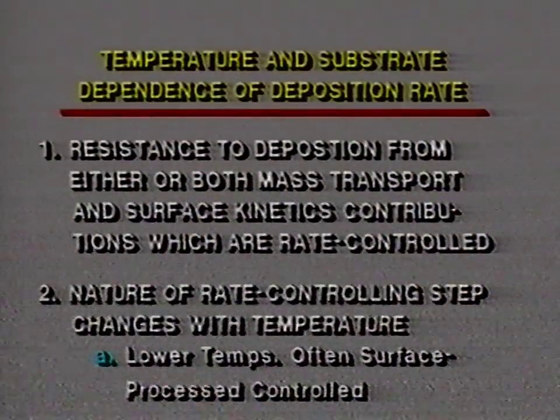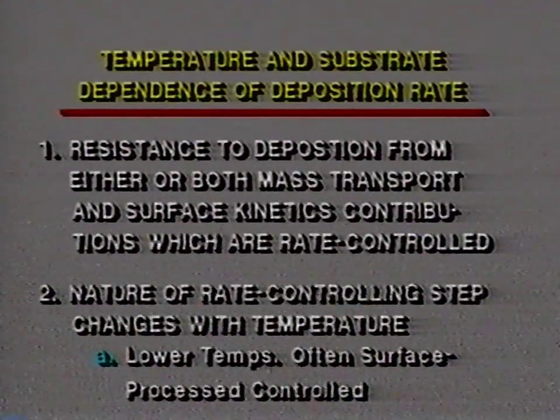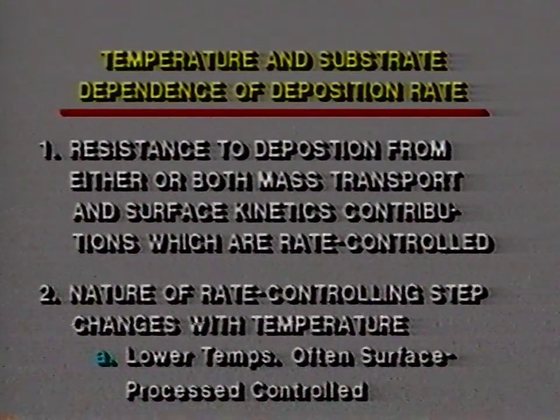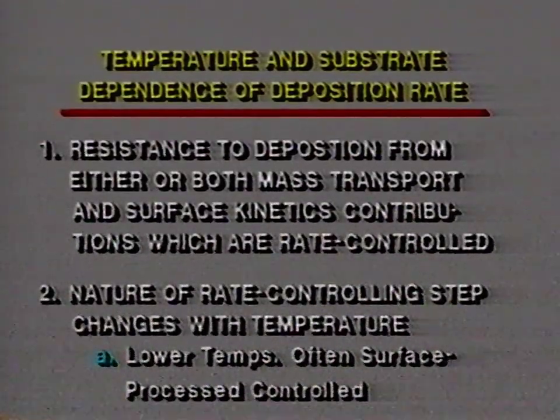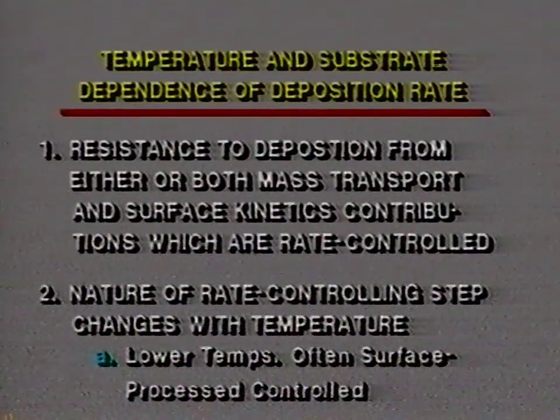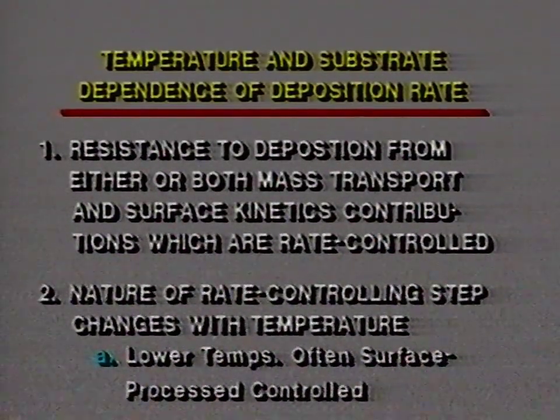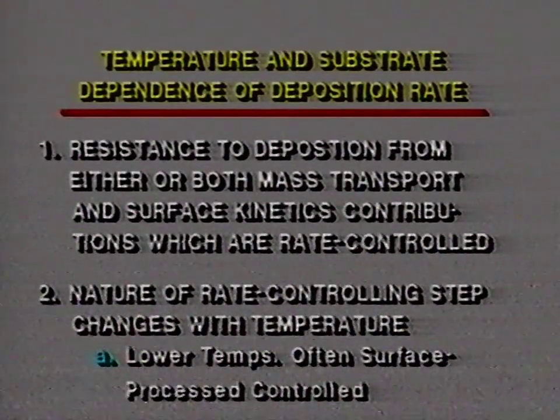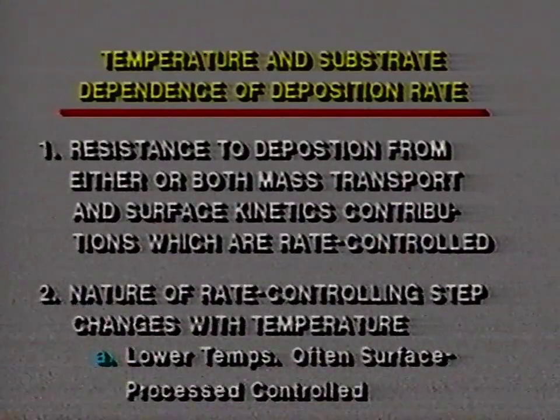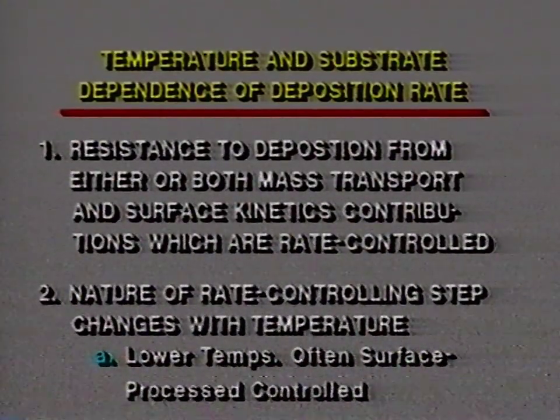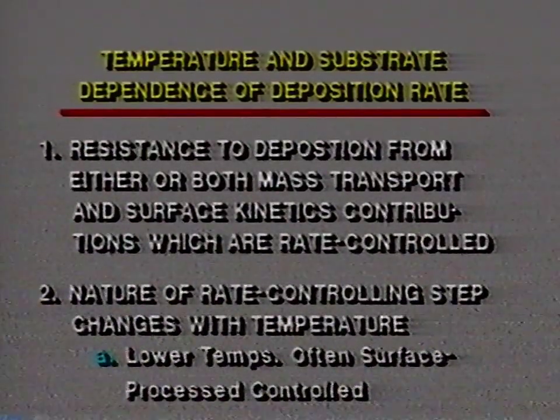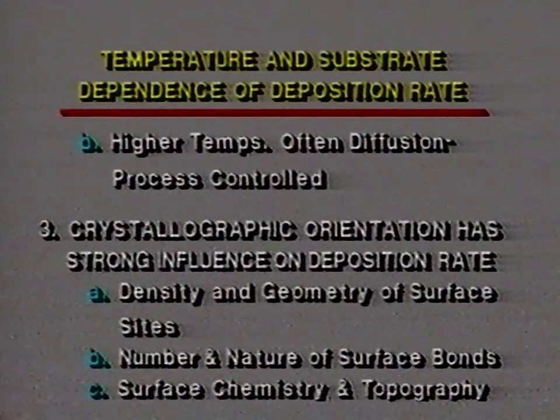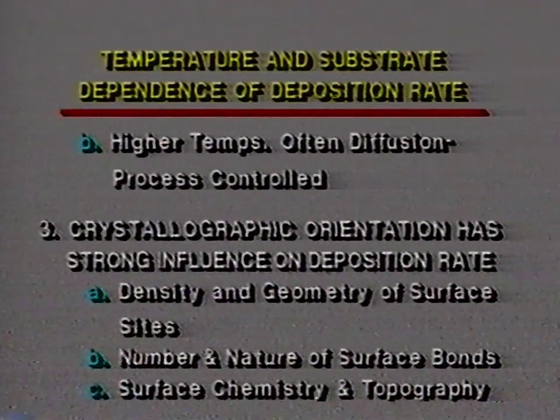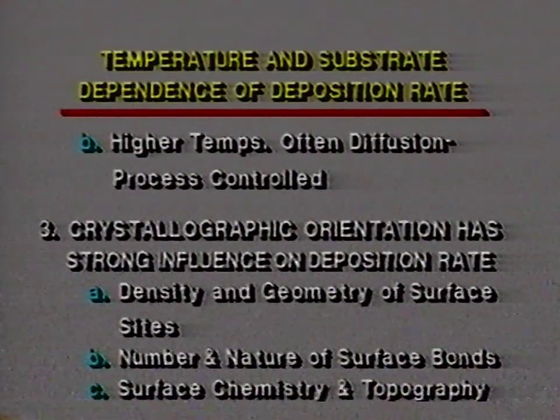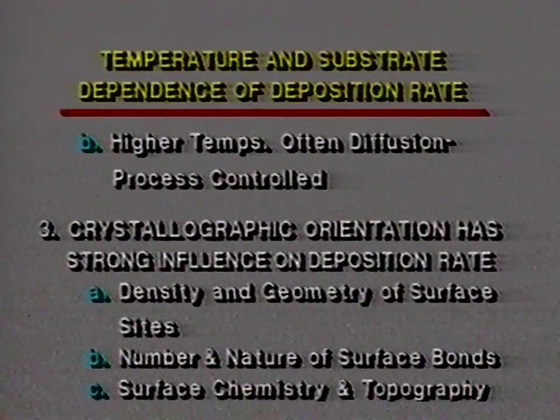If we look at another aspect of kinetics here, which is the temperature dependence, we look at number 2, the nature of the rate controlling step, which will change with temperature. Essentially, we have 2 types. One listed under A, which is at a lower temperature, is essentially a surface process that is controlled by exponential temperature dependence. And a higher temperature type of reaction is usually diffusion controlled, a diffusion type process, which has a mild temperature dependence, as we will see on the next slide here.